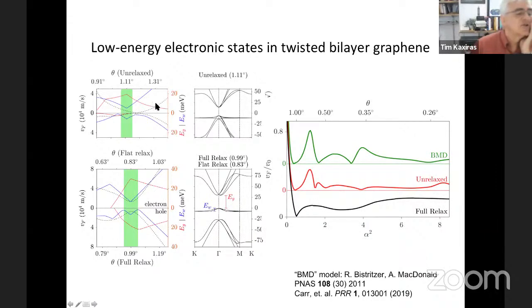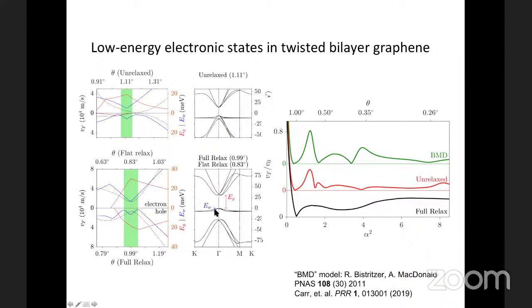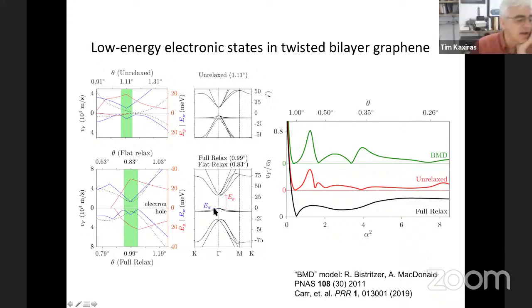Here is again the picture unrelaxed for the bands. This is just the flat bands at 1.11 degrees. And so on. So this is the picture with the full relaxation. And this picture now contains several important features in how they depend on the twist angle, including the full relaxation. So this is the picture that I want to describe in some detail. The blue lines here are the width of the bands, shown here schematically as the bandwidth, the flat bands. The red lines are the gap between the flat bands and the other bands.